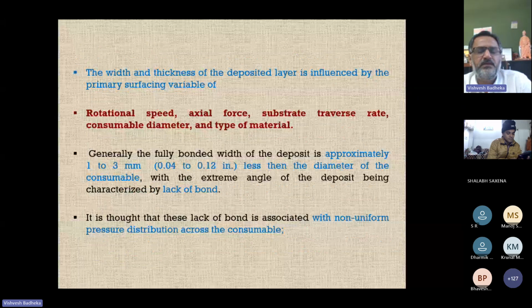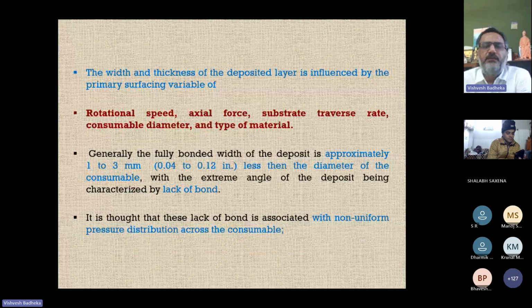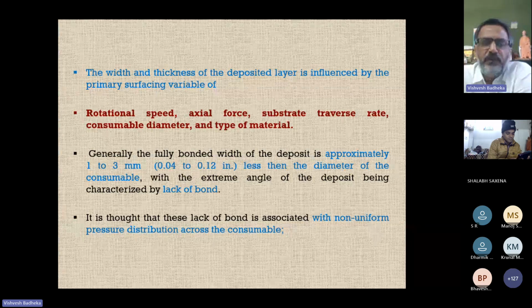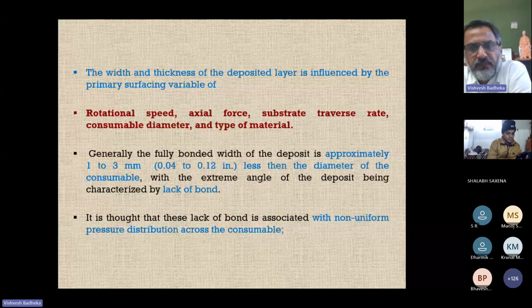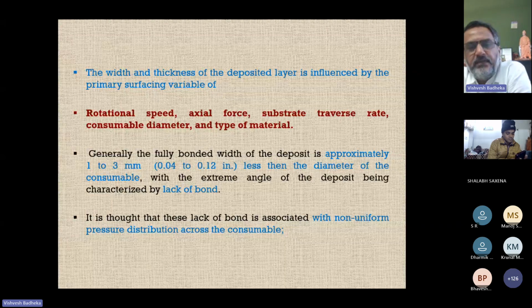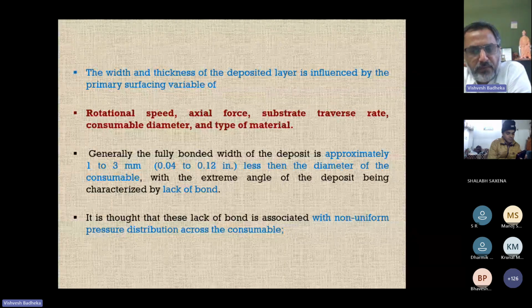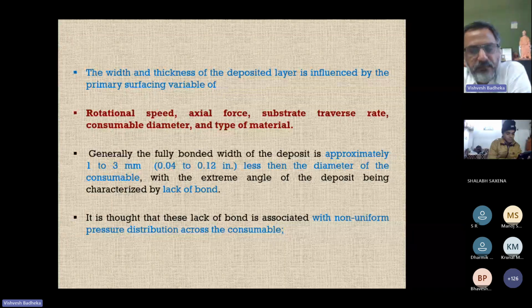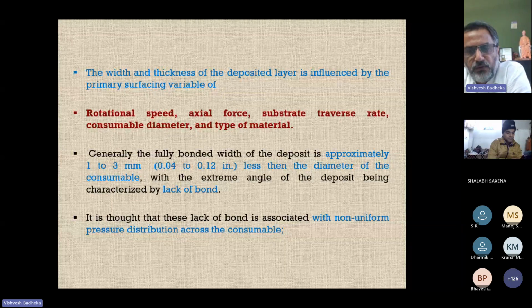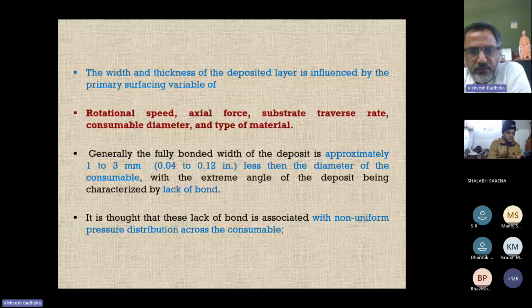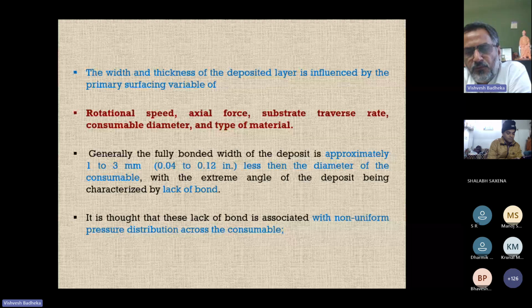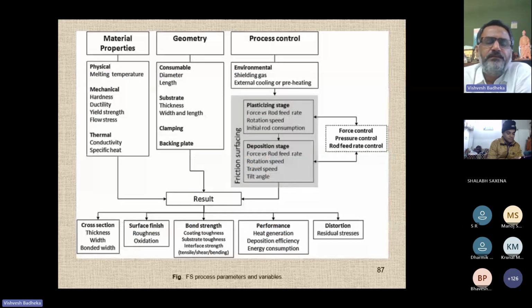As I already explained, the width and thickness of the deposit layer are very important, and they are influenced by the material combination. What is the rod material? What is the substrate material? And as I mentioned, bead width and bond width are two important parameters. What you are observing, 22 millimeter, is called bead width. But at the interface, what you are observing is the bond width, which will be less than the rod diameter. So there is always a lack of bond associated. These are the important parameters which will control the entire friction surfacing process.